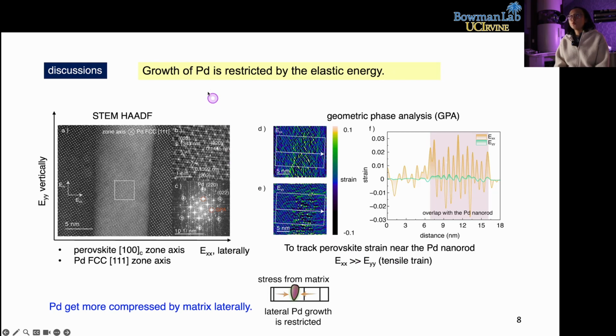We want to understand why at 0.15 millitorr the palladium will form palladium nanorods, and at 0.015 millitorr the thin film will show nickel cobalt oxide and palladium core-shell nanoparticles. For this palladium nanorod, we take the HAADF STEM image to show clearly how the matrix lattice looks, and also the atom arrangement in the palladium nanorod part. We can identify it using the FFT.